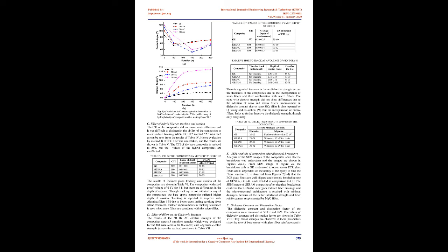Once the saturation level of water is reached in the epoxy matrix, water absorption continues into the space between the filler particles and the free volume. The tortuous water diffusion pathway is responsible for the requirement of longer duration for the occurrence of the second minima of Ca. These results confirm the existence of different zones of water as discussed by some authors, in Nanocomposites 8.